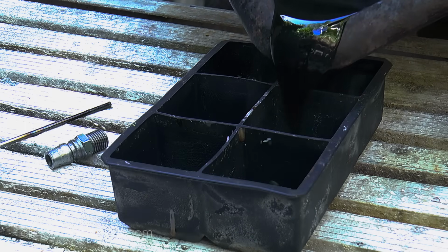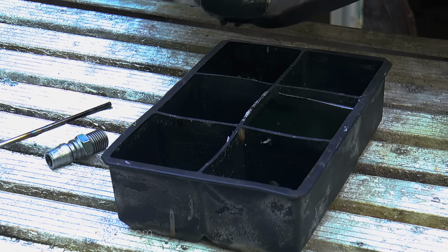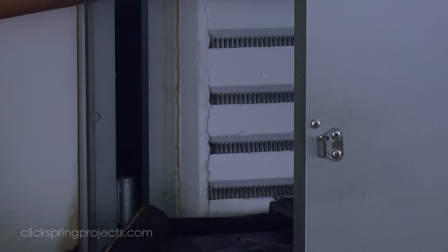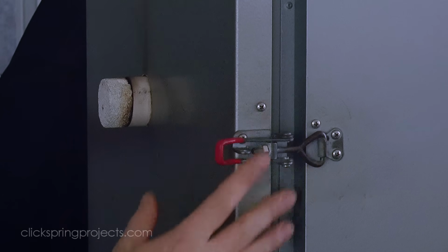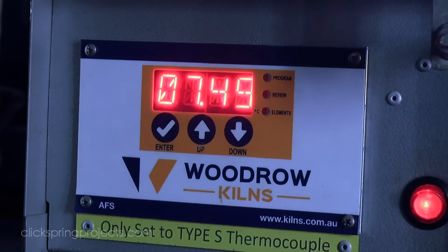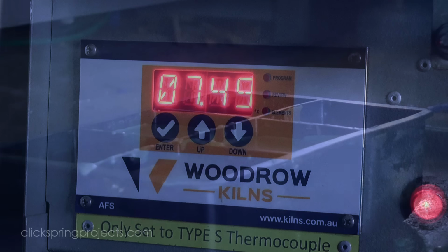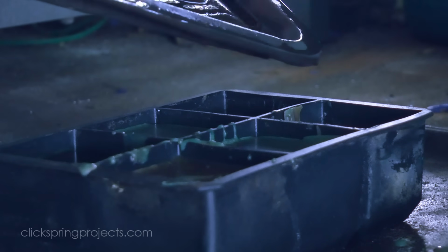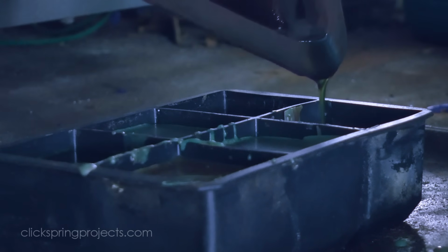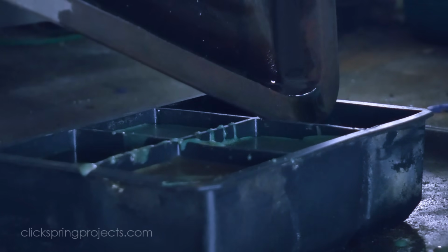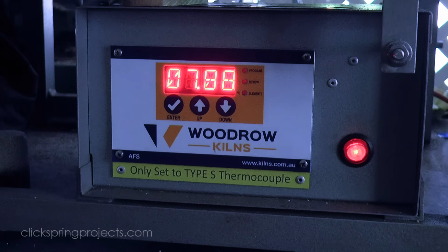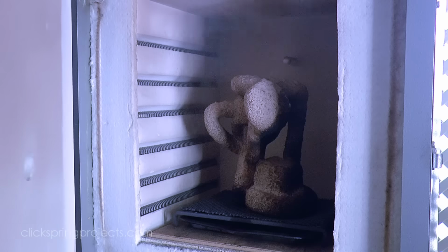I know the quantity of wax to expect, and the mould doesn't enter the kiln until I can verify that that amount has been removed and that only wax residue remains. The kiln schedule starts at 120 Celsius to first remove the remaining wax residue. Next is a ramp up to 300 Celsius for roughly an hour to start the process of breaking down the printed model.